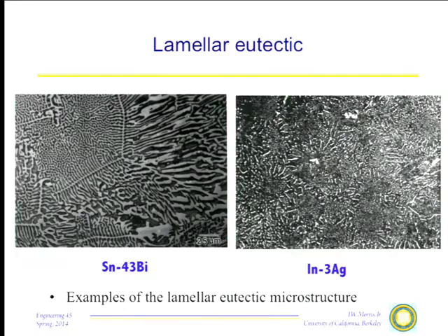Well, we can control these microstructures, and we do in things like soldering operations, because this, in fact, is a lousy microstructure from the point of view of mechanical properties. Your biggest problem in a solder joint in a microelectronic device is thermal fatigue. You turn your device on, it gets hot. You turn it off, it gets cold. Differential thermal expansion means that the poor solder joints are going like this. So before long, one of your joints breaks and your device won't work anymore, unless you're an intelligent engineer and whack the hell out of it, in which case the surfaces come back together and it works again. That's a kind of common problem.